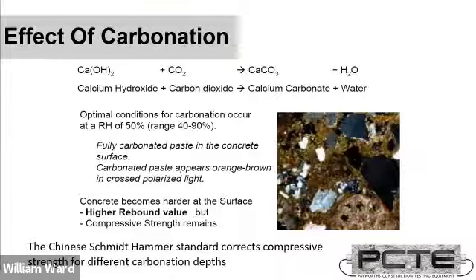But in the particular case of Schmidt hammers, it has an effect where while the compressive strength, the strength required to break that concrete, does not change, the surface hardness does. Schmidt hammers assess surface hardness, so there will be a higher rebound value where you have carbonated concrete. So older structures, this is of concern, or structures with particular exposure to carbon dioxide, like road tunnels.